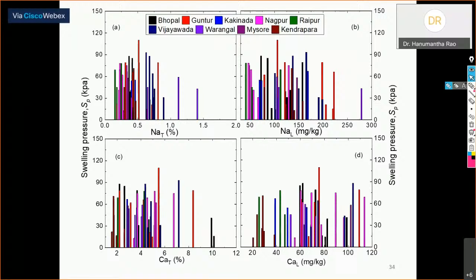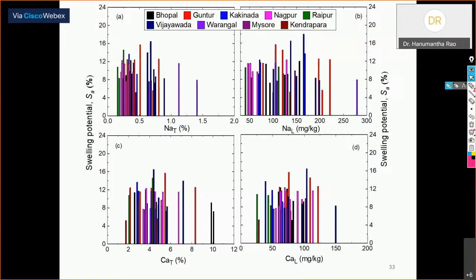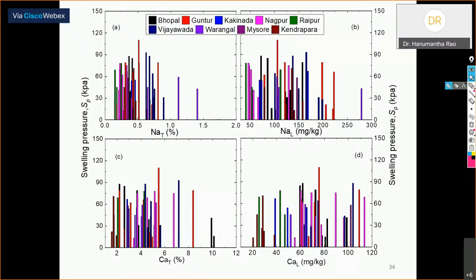These are the swelling pressure correlations with the total sodium or total calcium. One particular thing that we observed is that in the case of the SA, there is a well-defined correlation between swelling potential versus the sodium chemical parameter everywhere. But we did not find such a correlation when we tried to correlate swelling pressure with the total chemical parameter. As you can see in the bottom slides, there is a lot of scatter, or there is no definite trend. If you look at the left side, figure A, only in this case is there an increase in SP, it reached a peak and then decreased. But if you look at graphs C and D, we cannot say there is a perfect increment reaching a peak or decrement. There is some kind of undefined trend. That trend is not well defined.